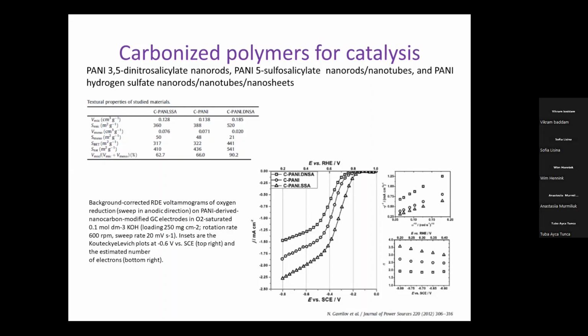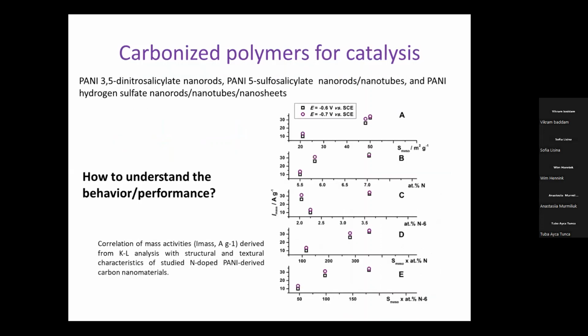And this electrochemical synthesis of hydrogen peroxide became especially interesting during Corona time. But then again, there is a question, can we understand how these materials behave? So we can correlate different properties of these materials. We can correlate some combination of these materials. So looking at only these three examples, we can see that, okay, there might be something with the surface of mesopores. There might be something indicating that nitrogen content or certain nitrogen species are important, but we still cannot be sure. And still in the literature, there is no consensus about the role of nitrogen in terms of electrocatalysis on carbon materials.